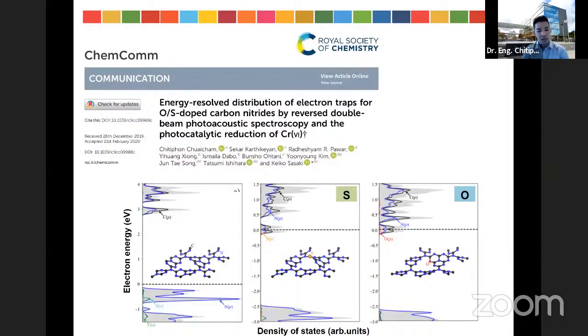So first, I would like to give you some examples of our work about the doping of the photocatalyst to reduce the energy band gap. In this work, we published in the Chemical Communications journal. And in this work, we modified the graphite carbon nitride by adding sulfur or oxygen atoms into the main structure of the graphite carbon nitride and changing the optical property. And we apply these materials for the photocatalytic reaction.